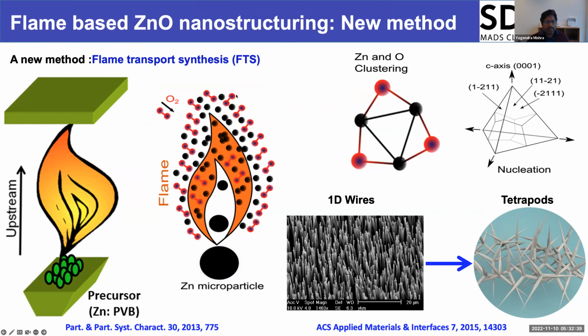The name of the process is flame transport synthesis, and there are several possibilities. If you apply a substrate on the top, silicon for example, then you can grow a one-dimensional array of nanostructures. And if you do not apply one, then you have the possibility to grow micro and nanoscale tetrapods, like you see here. First, we have nucleation. Initially, we have formation of octahedral nuclei, and then we have growth along four facets, more or less, because zinc oxide has a hexagonal wurtzite crystal structure, which is non-centrosymmetric, and the C-axis is the fastest growth axis from an energy minimization point of view. So that's how these structures grow.